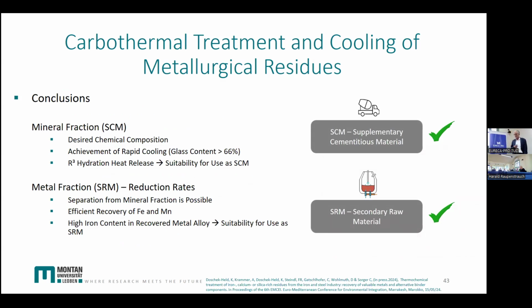What are the conclusions? By treating the material in that way, we get the desired chemical composition. We can achieve the rapid cooling, in this case with a glass content of about 66%. Talking about the metal fraction, we could separate the mineral fraction from the metal fraction. We could efficiently recover iron and manganese. And the iron content in the recovered metal alloy makes it suitable for use as SRM, as a secondary raw material in the metallurgical industry.